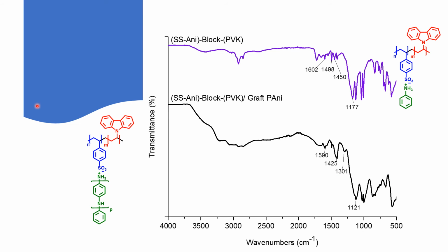The polymer system is insoluble. Because of this, we cannot analyze it by NMR spectroscopy, but employing FTIR spectroscopy, we can observe the signals of the quinoid ring and benzenoid ring, which are classic from polyaniline formation. Comparing the ternary system with the copolymer block, we can confirm the formation of the ternary system, which contains a styrene sulfonate, a carbazole substituent, and chains of polyaniline.